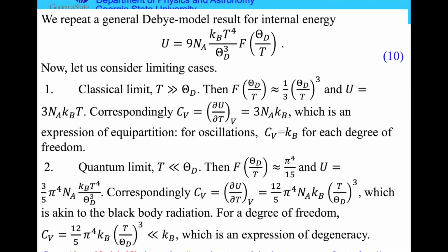One can ask what is the actual value of the Debye temperature for real crystals. It depends whether this is a molecular crystal, an ionic crystal, or a covalent crystal. The stronger the bond and the lighter the atoms, the higher the Debye temperature. In practical terms, the Debye temperature is somewhere from tens of Kelvin to thousands of Kelvin. Sometimes it's so large you cannot reach it. You will melt or dissociate the crystal before that. So it's a very wide range for existing crystals.